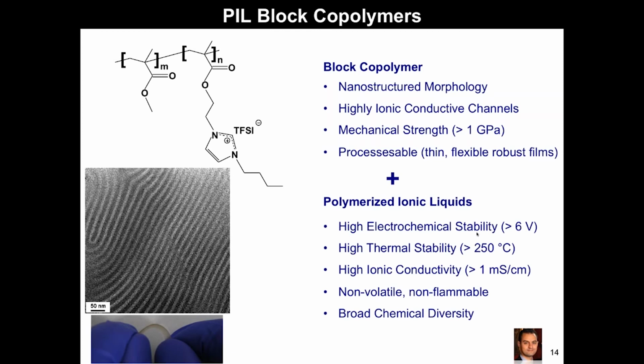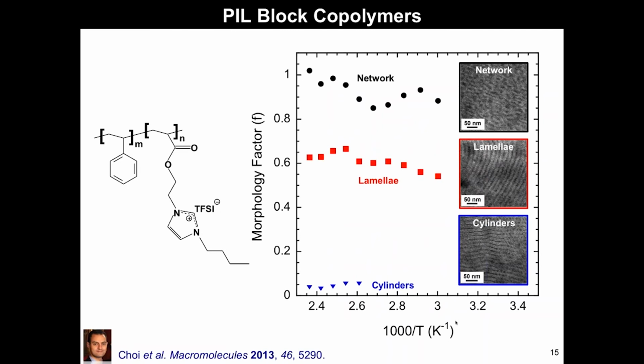So that's very attractive. And so if you look into the literature very recently, you'll see things like not only ionic liquids and polymerized ionic liquids in these applications, but now polymerized ionic liquid block copolymers. And it's really this broad chemical diversity which makes it interesting, because you can start to optimize all of these properties in terms of ion conductivity, mechanical strength, electrochemical stability. And here I'll just show you a couple examples of how block copolymers can impact ion conductivity.